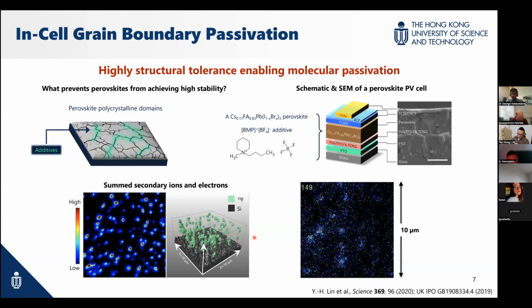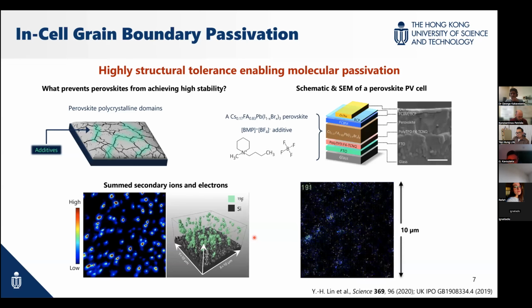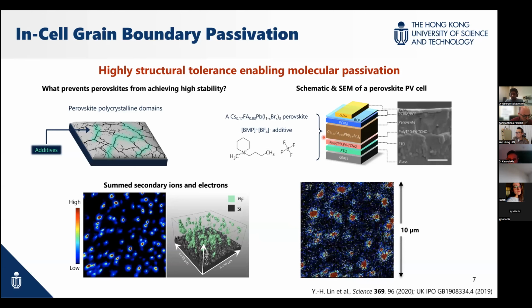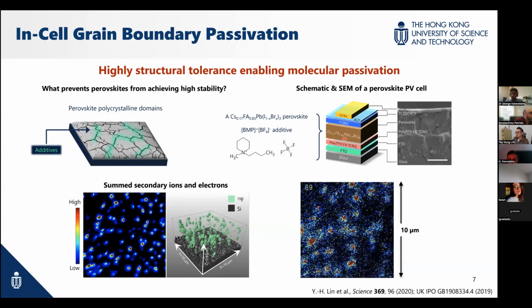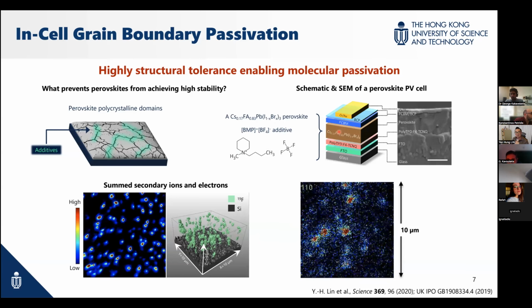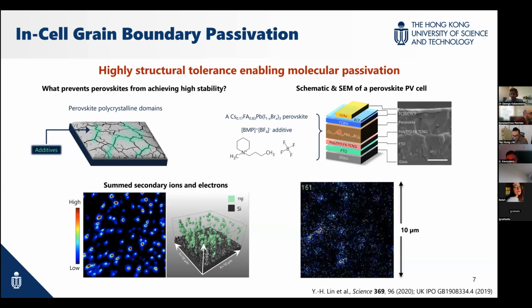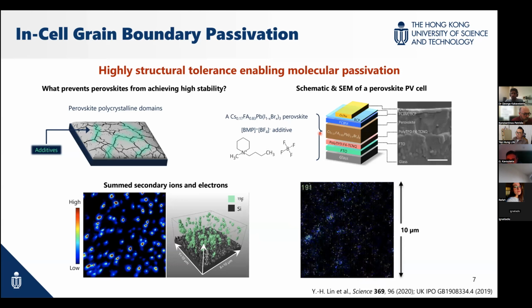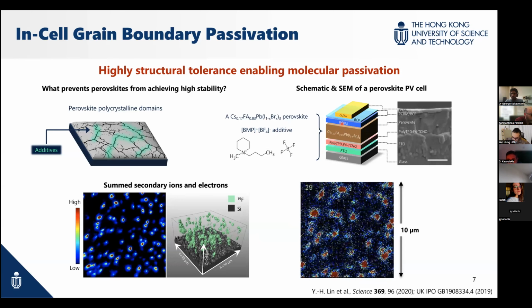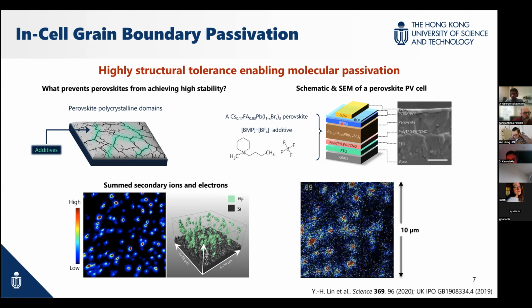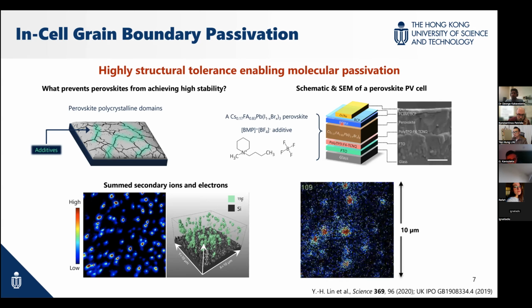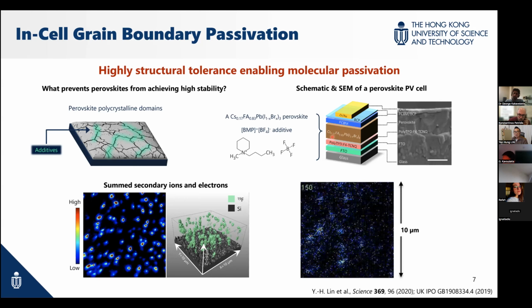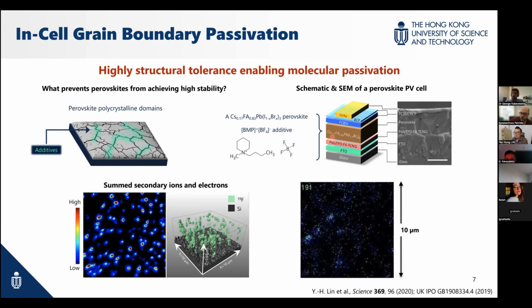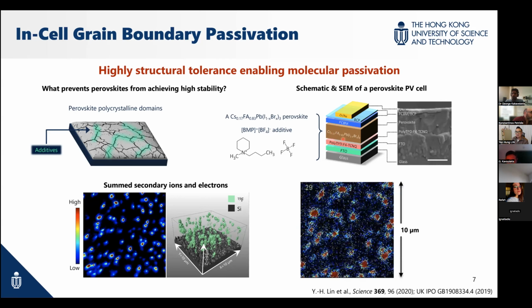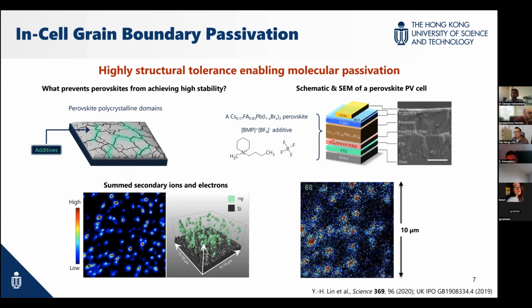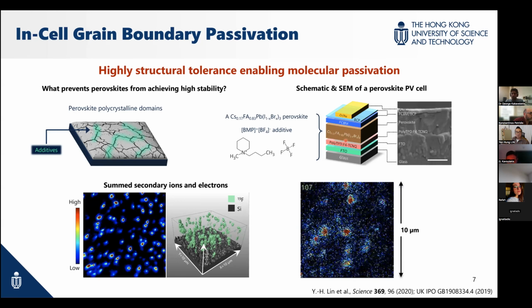So, okay, this is the second question. We basically blend it with the perovskite precursor, and for the device here, we didn't passivate the bottom or any part. We just add the additive into the perovskite material itself. Do we have new knowledge about this kind of passivation? Can we do it at the interface? We did try, because before this work there was also another work, BNI and BFO. So we did try different approaches to work at the interface, but the interface is relatively difficult to control in amount. Because it can be blended into the perovskite precursor, if we put it at the bottom, it will partially dissolve into the perovskite material, but it also remains a little bit like particles at the interface.